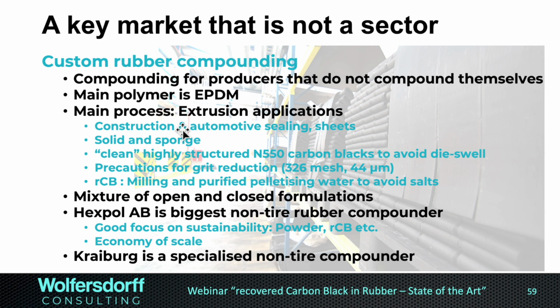So for the sealing profiles, especially the outside automotive sealing profiles, everything needs to be very, very smooth. The sealing profile is the first thing you look at when you open your car door. It needs to be very, very smooth. And this is not really about the carbon black being gritty, but the so-called grit on the 326 mesh, which is about 44 microns. The grit is coming from the water and the salts in the water that are used for the pelletization. Or in the case of the furnace carbon black, another source is the quench water, the quench that stops and controls the furnace carbon black reaction.